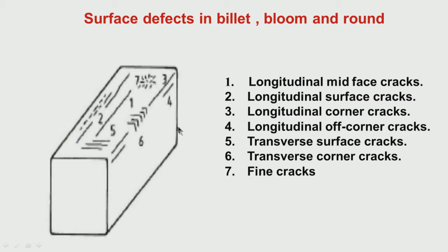So, depending on the location and the direction, we call them longitudinal, transverse, or mid face. If we are at the middle of the face, we call them mid face. If it is random, we may call it normal surface cracks. If we are at the corner region and the direction is longitudinal, it is a longitudinal corner crack. If the direction is transverse, we call it a transverse corner crack.